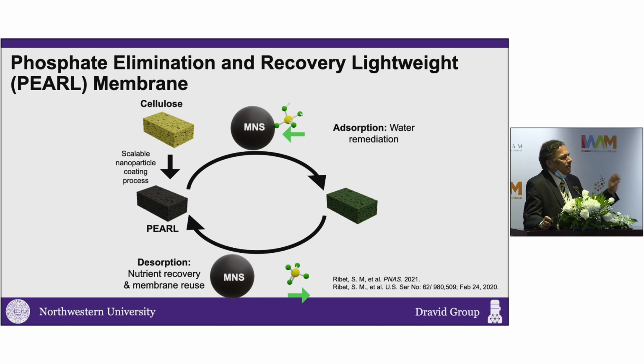So imagine, just like in the oil case, we are squeezing the oil out and reusing it. Here, instead of a physical squeeze, it's a chemical, pH-dependent process. So imagine a bunch of sponges. In fact, we are doing testing in Florida and other locations where there are phosphate ponds. As some of you may remember, last year there was a risk of a pond being close to breached. And there was a lot of concern in Florida about this excess phosphate being released into oceans. So here we have a low pH, absorb phosphate, high pH, release it, and you keep on doing that. And that's the idea behind the phosphate recovery.